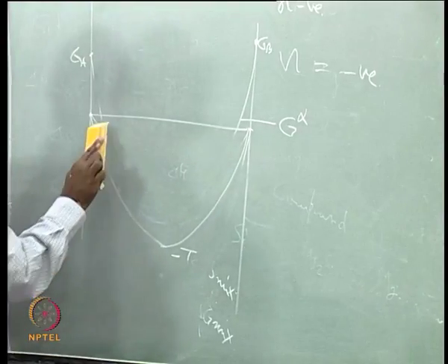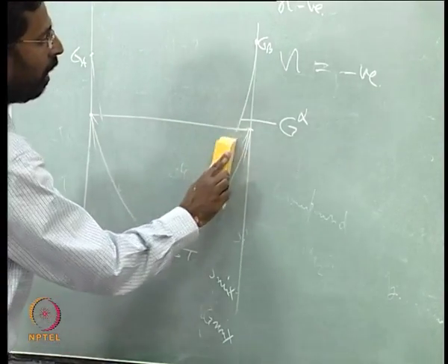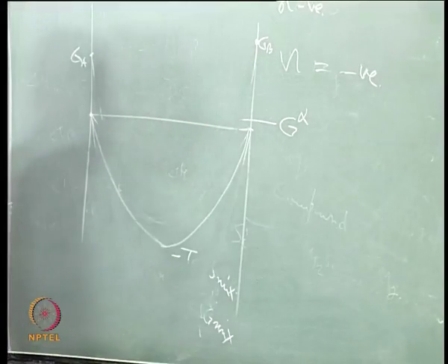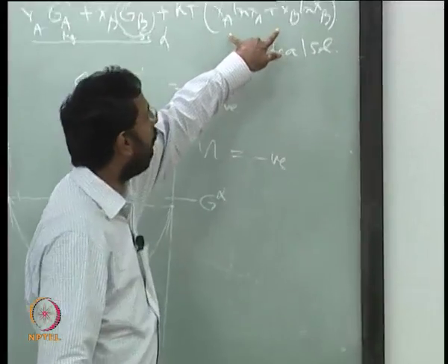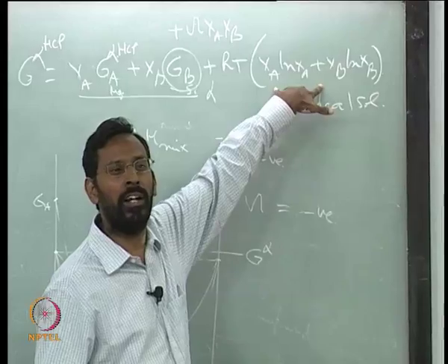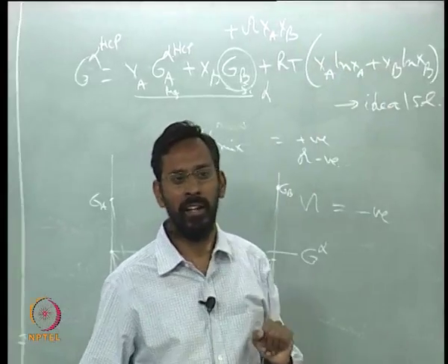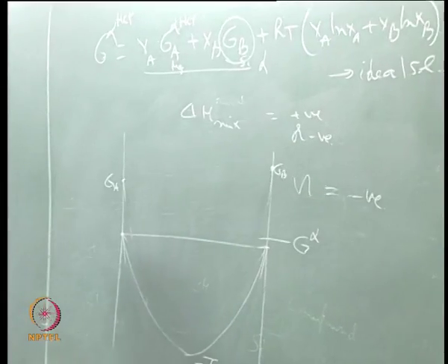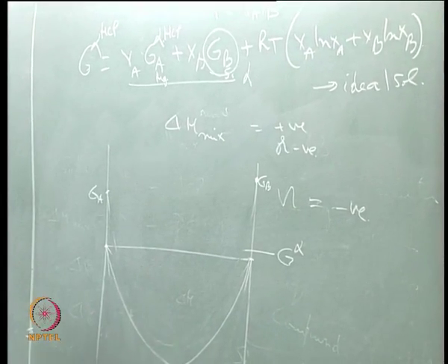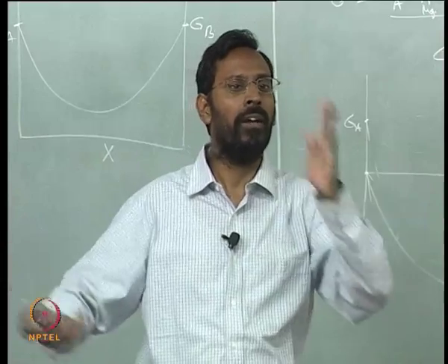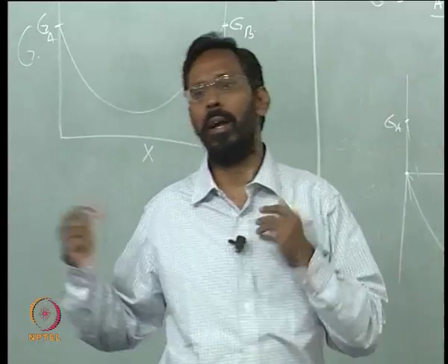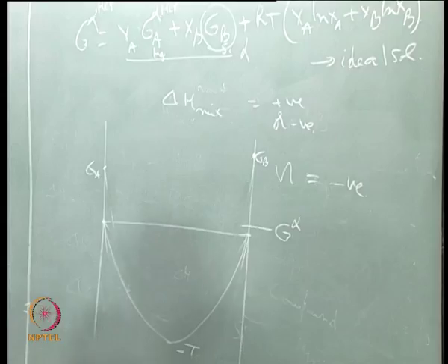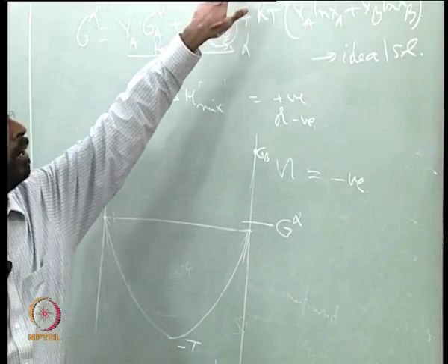So, I say that entropy of mixing is not changing, obviously it will not change, is it? Any system that I choose, entropy of mixing is the same. We said before that this part is unbiased by what element it is, because there is no element coming in there, it is simply composition. So whether I take nickel aluminum system or magnesium silicon system, it will have the same configurational entropy whenever I take a 50-50 composition. It does not depend on whether it is nickel aluminum or magnesium silicon. What comes in terms of what is the system, it is here.